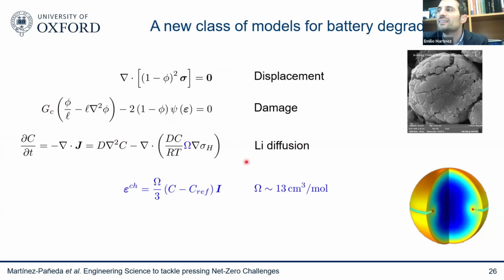Again, a similar problem. And different to the hydrogen problem, the lithium causes chemical strains. Hydrogen also causes chemical strains, but they're small. They're very small because the partial molar volume is quite small. It's an order of magnitude larger in lithium. But as you can see, all of these things rely on physical properties that we understand, that we can measure, and therefore phenomena come naturally. We don't need to make any big assumptions.